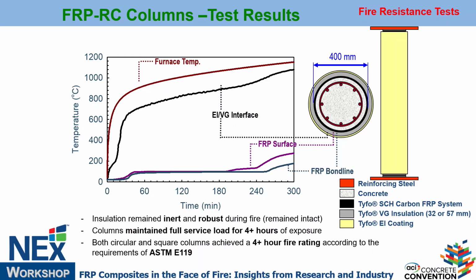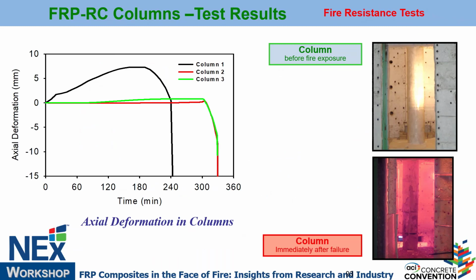As you can see, this is in minutes. And this is FRP temperature. As long as you keep the FRP temperatures cool through the insulation, no problem. You can get 4 hours in this case for a column, a huge column. The column which was tested was 16 inches square or circular. Now, this is where the glass transition temperature is reached. After that, you can see the temperature starts to go up, right? And the column starts to deflect.